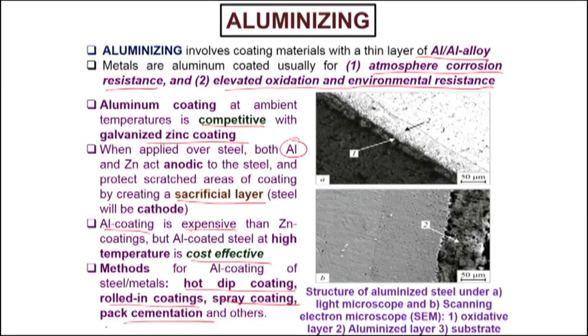The important thing is that the coating we apply actually grows with time. When we coat aluminium on steel, the cross section shows a coated layer and also an inter-diffusion layer. The first layer will be very rich in aluminium, and then aluminium concentration as a function of depth will decrease, and then there is the substrate which is unaffected. This layer thickness will depend upon the process parameters — typically the chemical potential, temperature, time, and so on.